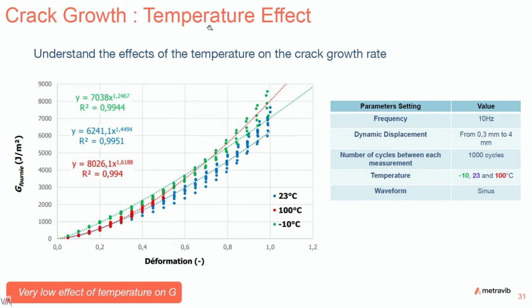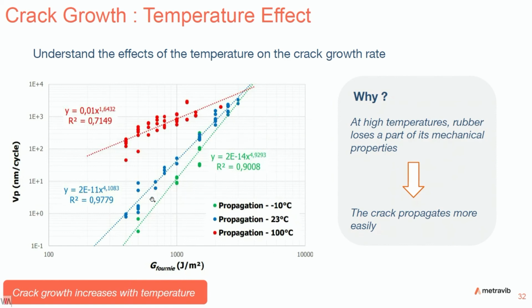What about the temperature effect? Same observation, G as a function of the deformation. Once again, you can find a very low effect of temperature on G, the tearing energy, but crack growth rate increases with temperature. At high temperature, rubber begins to lose part of its mechanical properties, and finally the crack propagates more easily. Three different temperatures are shown here: -10 degrees, room temperature, and 100 degrees.